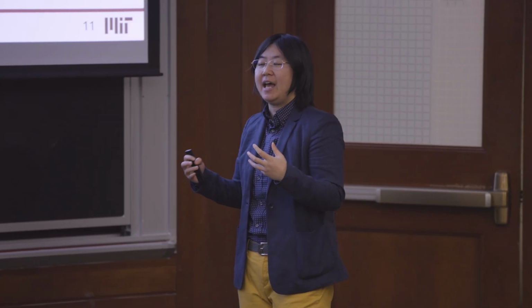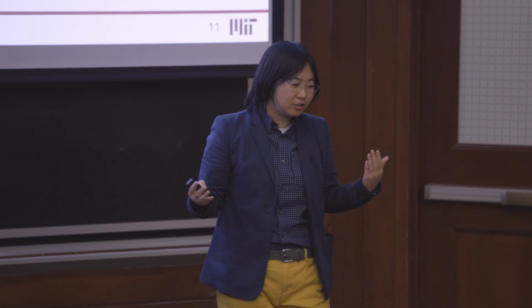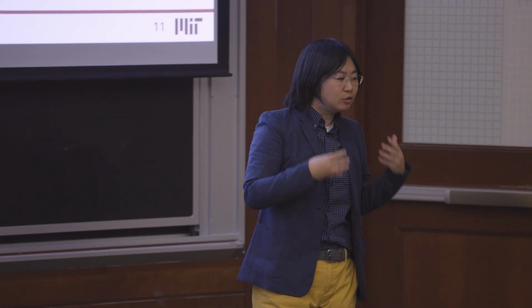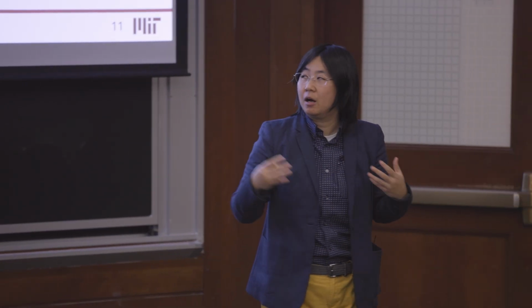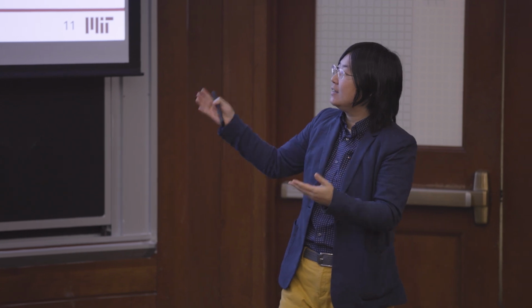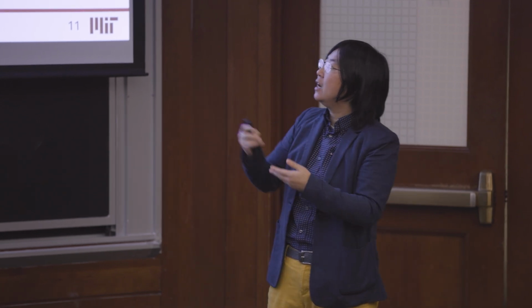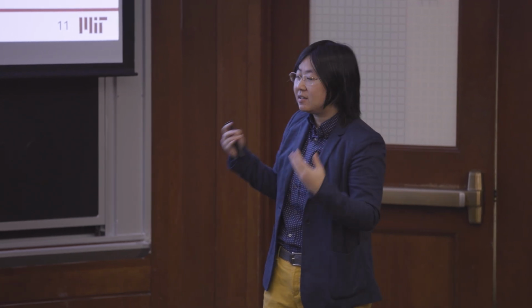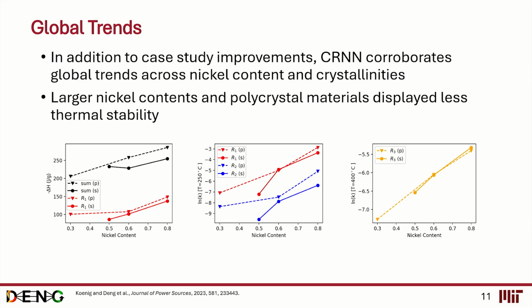After that, we would be able to apply this to a wide range of materials to understand why certain materials are more thermally stable compared to other materials. For example, we can compare the trend of different nickel content and make sense of why a higher nickel content is less thermally stable because of the decrease in the activation energy, and so on, and be able to understand why single crystals are more stable than polycrystals.